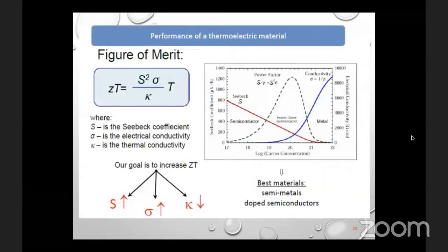The efficiency of a thermoelectric device can be improved generally by increasing its thermoelectric figure of merit. You can see the formula here, where S is the thermal power or Seebeck coefficient, T is the temperature, sigma is electrical conductivity, and K is the thermal conductivity, which is written as the sum of lattice and electronic contributions. So a good thermoelectric material has high thermal power, low electrical resistivity, and low thermal conductivity.